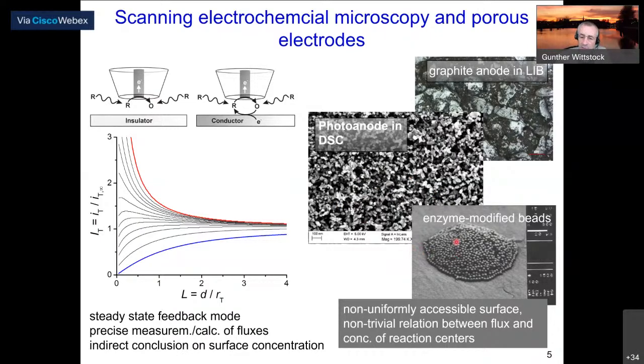And here's another example from the area of biochemistry, where enzyme-modified polymer beads are very often used to manipulate proteins and in assay procedures. And such a bead mount is also a porous material, and treating that as a smooth surface is not correct, because we have a three-dimensional volume contributing to a conversion. But in that three-dimensional volume, not all of the beads are uniformly accessible, so it's more complicated to reach by mass transport one of these beads which is deeply buried compared to one which is at the surface. And that makes also the evaluation of such data non-trivial.